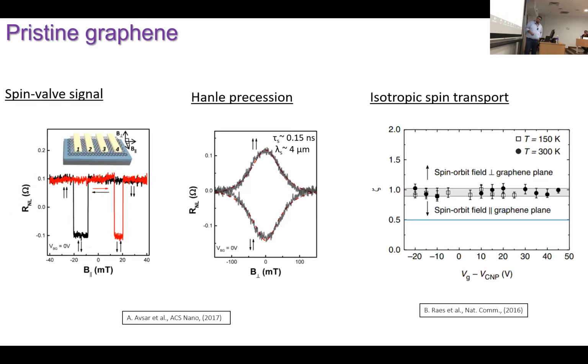Okay, so before showing you anything with the black phosphorus, let me show you the typical measurement we did with graphene. So this is graphene encapsulated with boron nitride crystals. I will not go into detail, but the top hBN is serving as a tunnel barrier for efficient spin injection into the material, and the bottom hBN is working as a high quality substrate to increase the mobility of the devices.